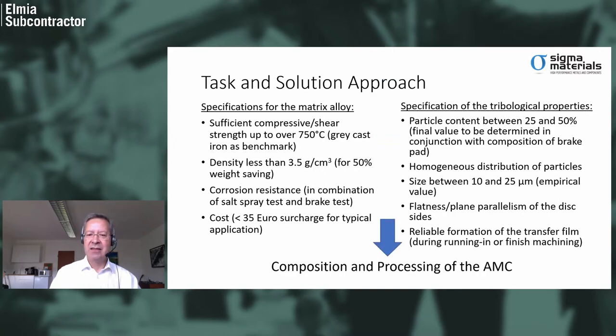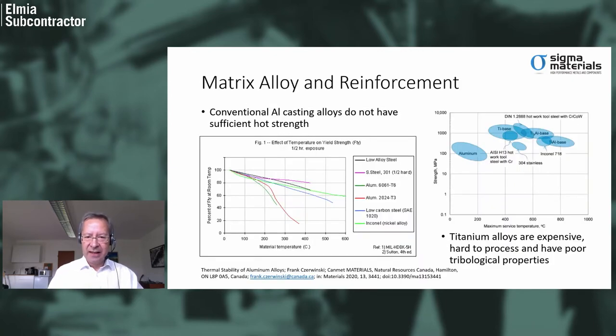So this is our holistic solution approach, because we have to regard all these aspects and bring it all together in a solution for an MMC or AMC, aluminium matrix composite material. The issue, as described, is that conventional casting alloys soften at above 250-300 degrees. So typical maximum operation temperatures are 350 for pistons for combustion engines. In brake discs, where we have predominantly compressive stress, this can be extended to 450 degrees because the hard particles support the compression very nicely. On the other side, when we look at alternatives, we see that titanium alloys are very expensive, hard to process, and also have poor tribological properties, so it's ruled out at the moment.